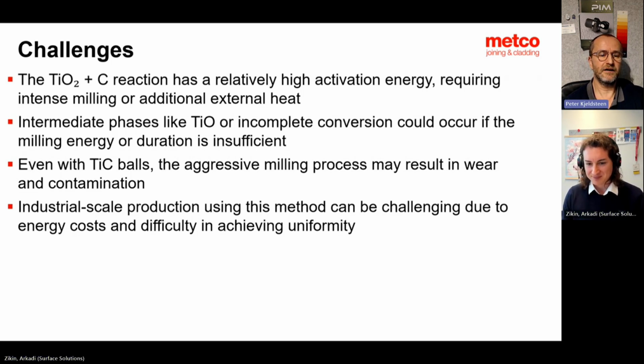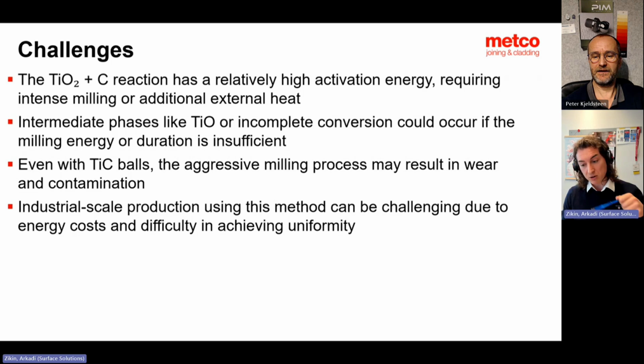I was a little in doubt when you told that you could just put in the energy to reduce the titanium oxide with carbon at room temperature. I might doubt temperature. Of course, mechanical loading causes a temperature increase, but you need certain long cycles for the transformation to take place. I can assure you that we got titanium. I personally did it in the lab. On a lab scale, it has functioned.